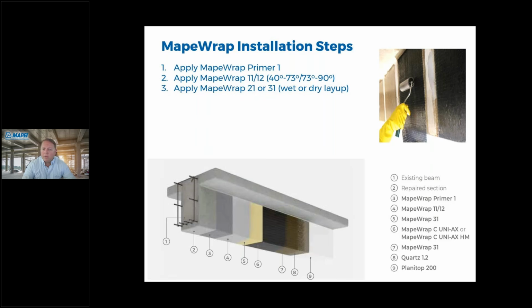And then there's the MapeWrap 31. This is a dry layup system where you're going to be putting the fabric on dry. So you put the primer, your epoxy adhesive, and then you'd roll with a nap roller some 31 resin. You install the fabric dry, and then you go back again with that nap roller and roll another coat of the 31 epoxy on there.